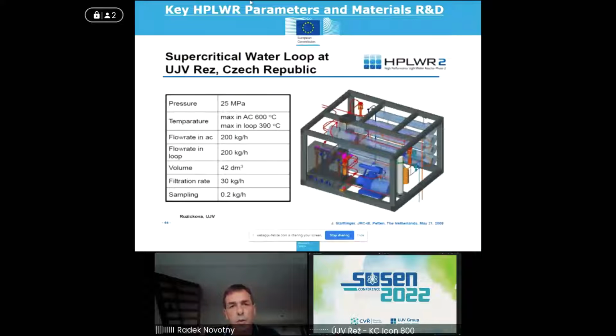I should also mention the supercritical loop, which was designed and built by UJV. I'm mentioning it because it's probably the most advanced testing facility we have at the moment in the community, because it is using very high flow rates. First of all, it's the only device we could use in cores for radiation studies, and second, it's the closest we could get to the real flow rates in a real plant, because it's using very high flow rates up to 200 kilograms per hour of water.